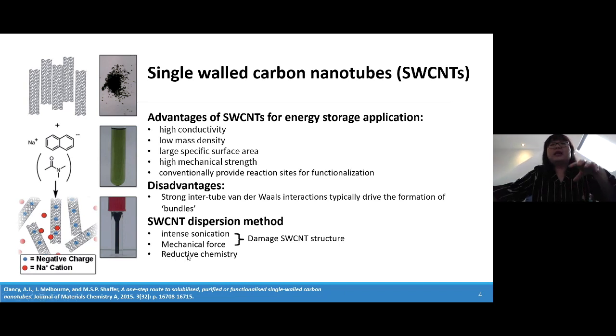So in my research group, we study another approach, which is called reductive chemistry. Reductive chemistry normally uses alkali metal solutions to create negative and positive charging in the system of the solutions. In my case, I'm using sodium naphthalide to create negatively charged single-wall carbon nanotube solutions in the solvent. And the results have been studied by Adam Clancy's team, showing that this method can make the SWNTs soluble easily in the solvent and also doesn't damage the SWNT structures.